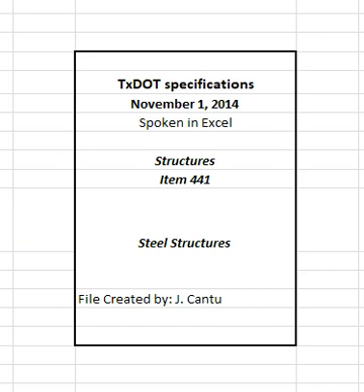Retest repaired groove welds per the applicable AWS code after repairs are made and have cooled to ambient temperature. Complete NDT and repairs before assembly of parts into a member, but after any heat correction of weld distortion.